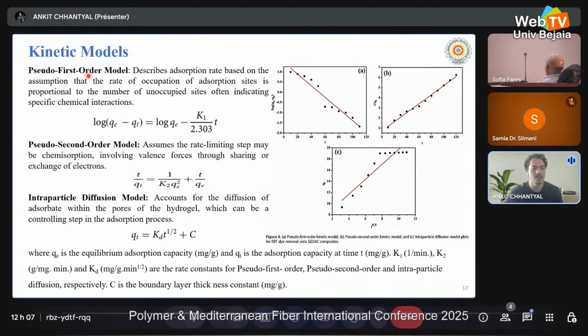First one is the pseudo first order model, which gives the rate of occupation of adsorption sites, which is proportional to the number of unoccupied sites, often indicating a specific chemical reaction. And this is the equation: log(Qe minus Qt) is equal to log Qe minus K1 t upon 2.303, in which Qe is the equilibrium adsorption capacity, and Qt is the adsorption capacity at a particular time, whether we are in the series of time, like 10, 20, 30, 50, whatever the minutes in which your dye or heavy metal ions are adsorbing. And K1 is the rate constant for the pseudo first order model.